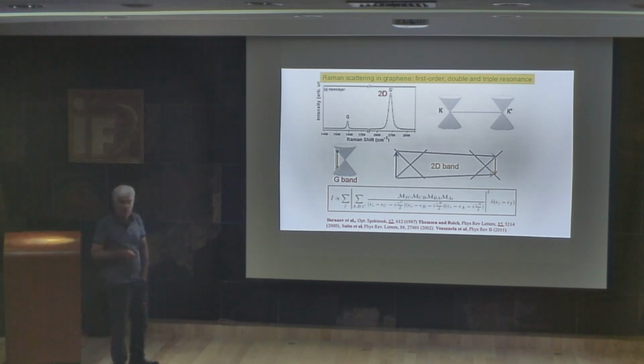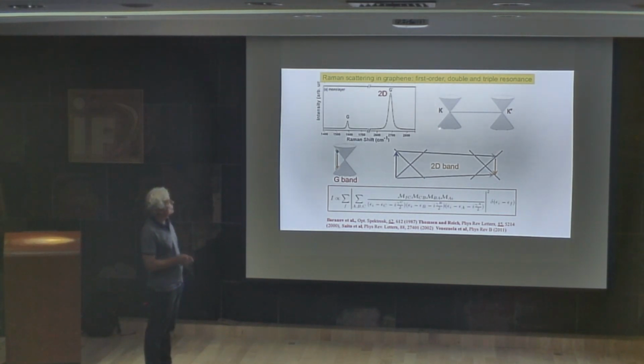But we have also a very interesting band in graphene that we call the 2D band. The 2D band is a higher order process because it involves electrons in different cones of the Brillouin zone, at the K and the K prime. I don't have time to explain in detail, but this band is like that. One incident photon is absorbed, creating one electron-hole pair. The electron is promoted from the valence band to the conduction band. But then there is one strong electron-phonon interaction.